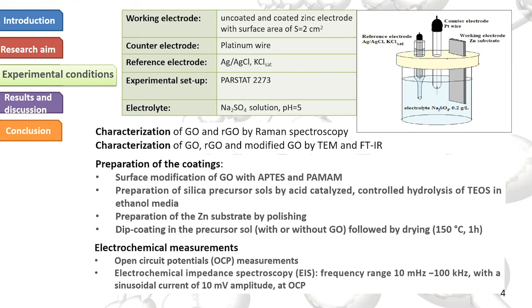Important is that we use the 3-electrode system with sodium sulfate electrolyte in order to investigate the coated and uncoated zinc substrates electrochemically. Before that, we studied the GO and RGO by Raman spectroscopy. We modified the GO and investigated the graphenes by TEM and FT-IR. About the preparation of the coatings, we used the dip coating method. We had 5 precursor sols, the silica sol, and the other 4 containing the graphenes. After dip coating, a drying process was necessary.